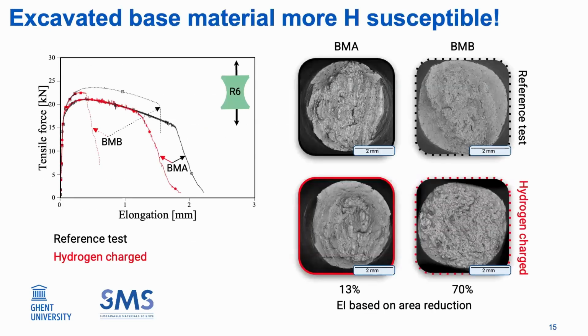As expected, the performance of both these materials degraded in the presence of hydrogen, more for BMB, as can be seen in this plot, as compared to BMA. The fracture surfaces also show mostly quasi-cleavage or a brittle kind of fracture for the hydrogen-charged BMB. To put a number to it, the hydrogen embrittlement index of BMB was 70% in contrast to 13% for BMA. And this is based on the area reduction part of this curve.